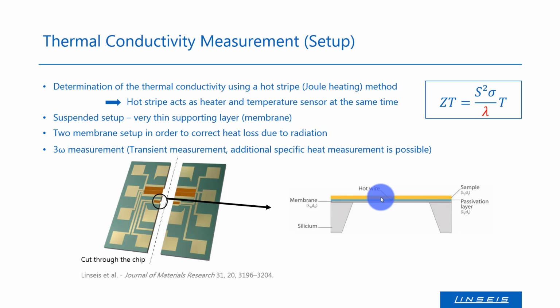For example, the higher the thermal conductivity of the sample, the smaller is the temperature rise of the hot wire at constant heating power. As we do not use constant current but alternating current to drive the heater, we can use the third harmonic of the voltage drop along the heater for the temperature measurement. That's why the measurement technique is called 3-omega measurement technique.